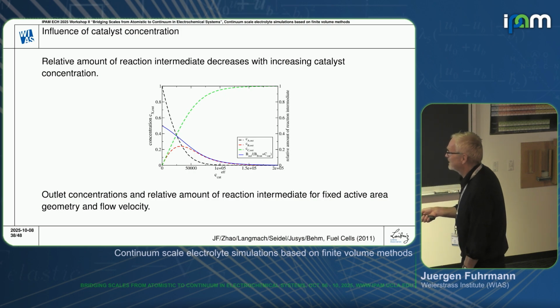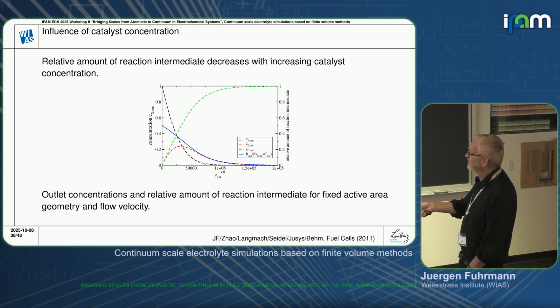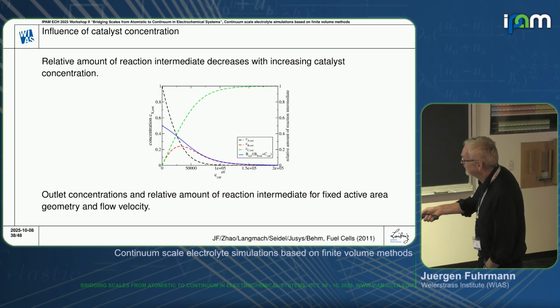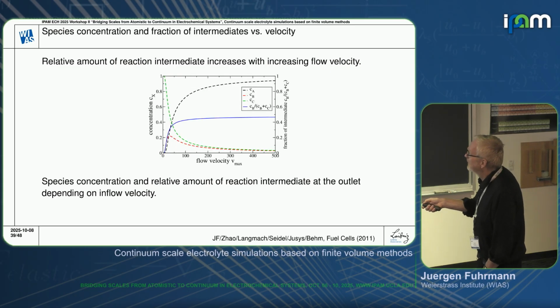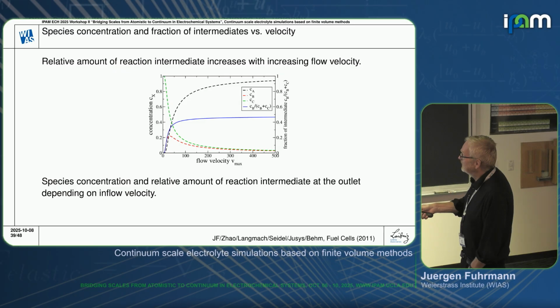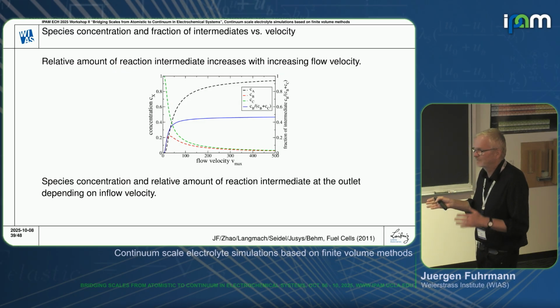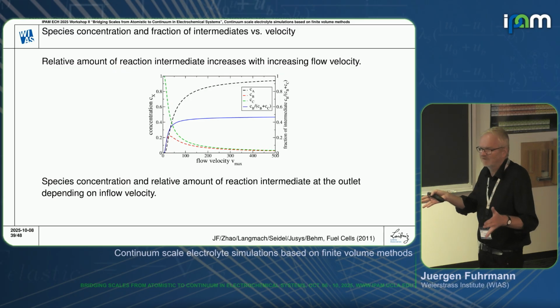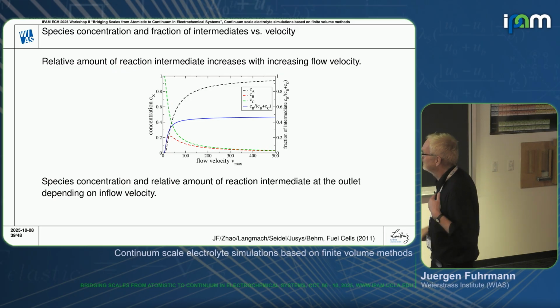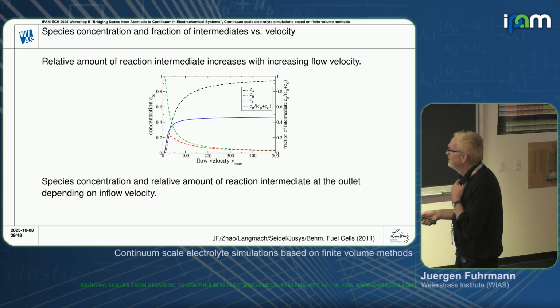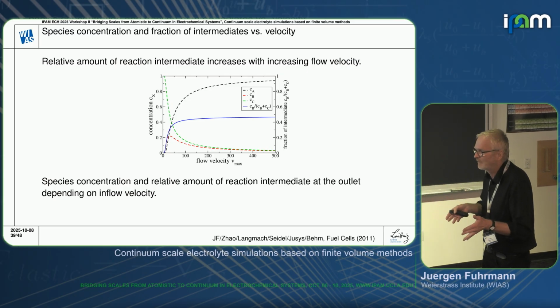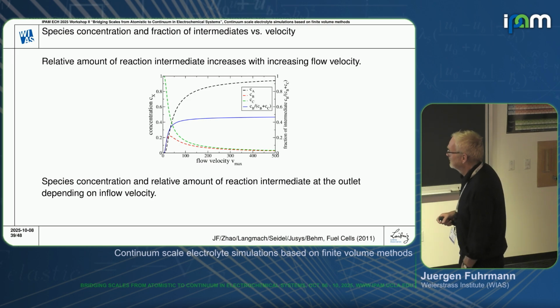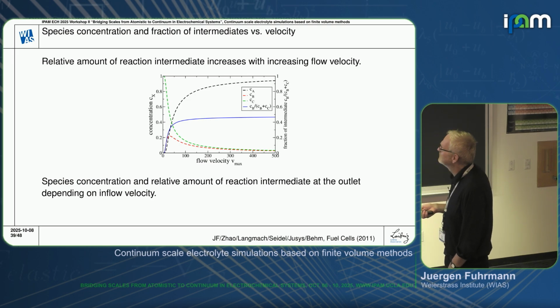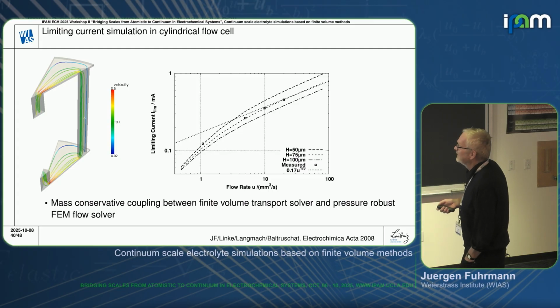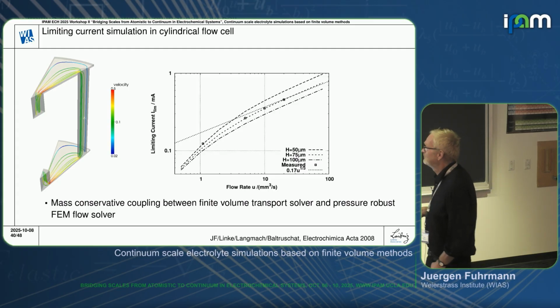And we see very much the same effects where we have just the relative amount of the reaction intermediates, the blue curves, decrease with increased catalyst concentration. And it increases with increasing flow velocity. So that means from this kind of relatively simple modeling, which then includes the convective diffusion transport, we can see already the effects which had been found in the experiment, which then can partially at least explain what has been measured.